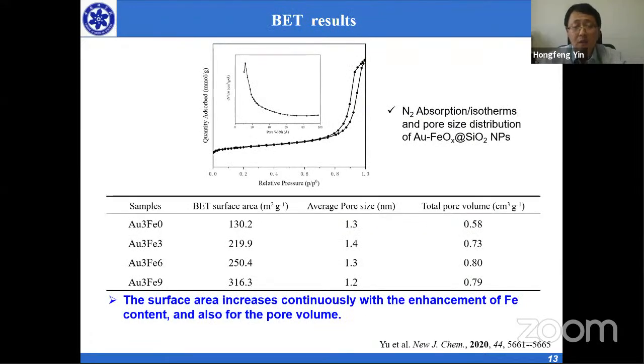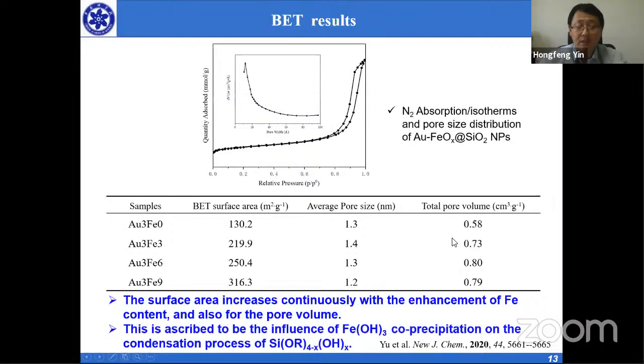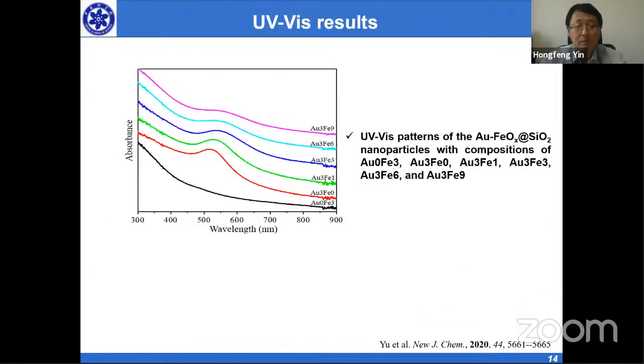This is the BET result. We can see that with the introduction of iron, the surface area increased from 130 to 316, while the pore size didn't change much, and the total volume also increased. This is because of the influence of the iron hydroxide co-precipitation on the condensation process. That will make a pretty big pore volume.